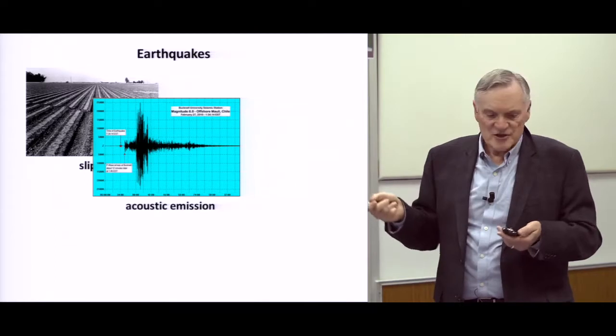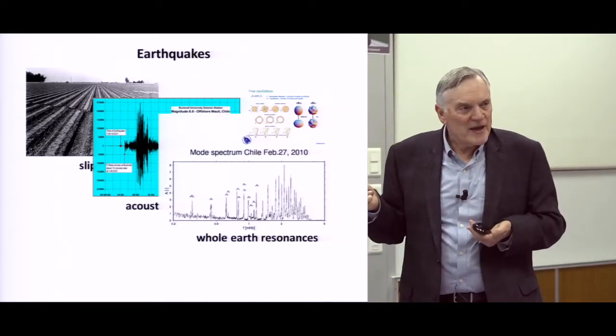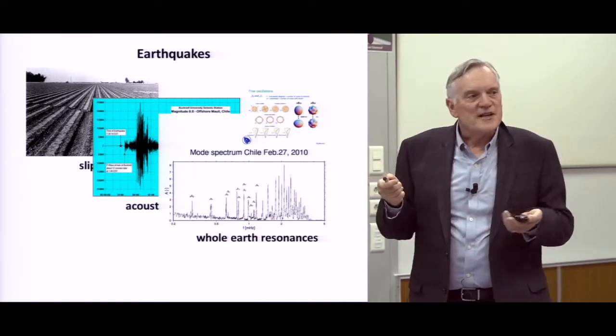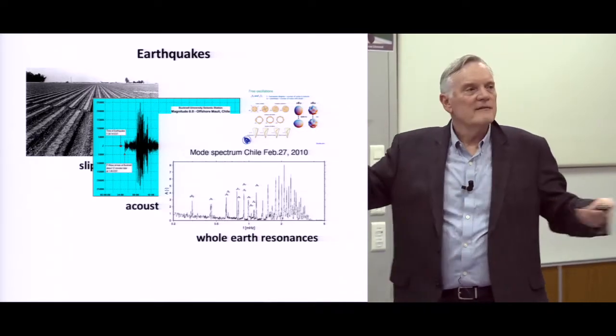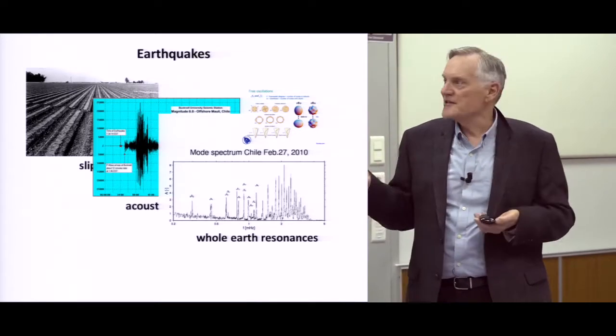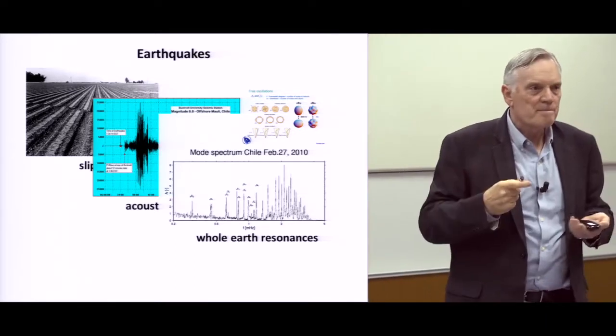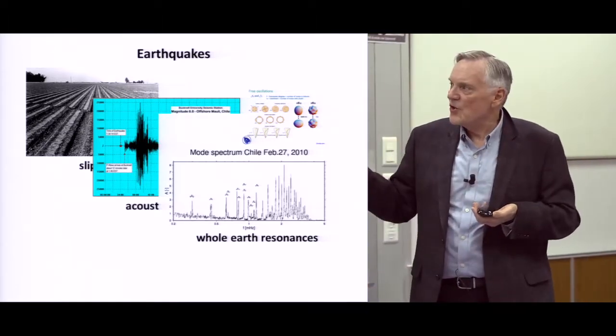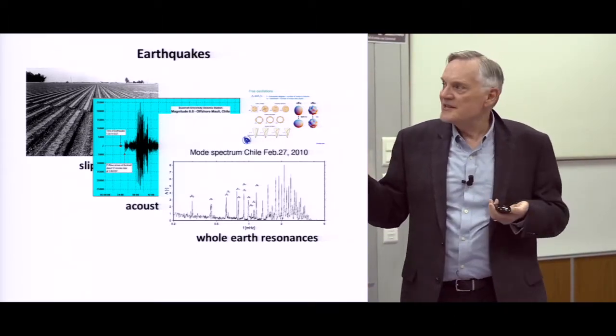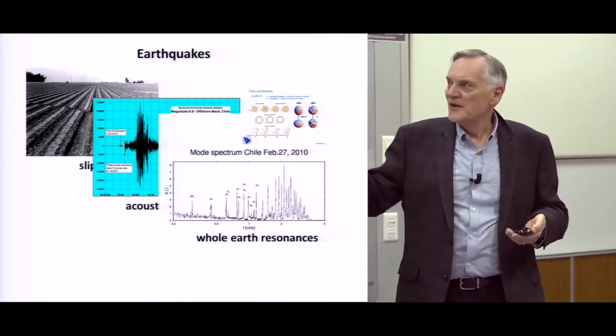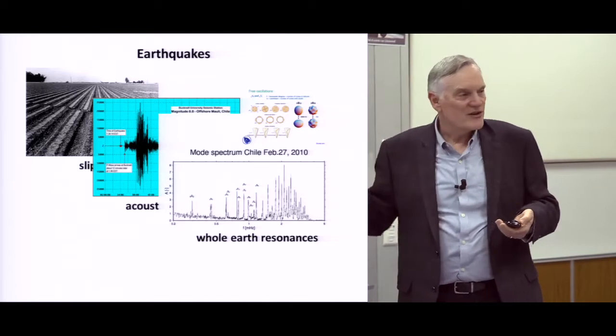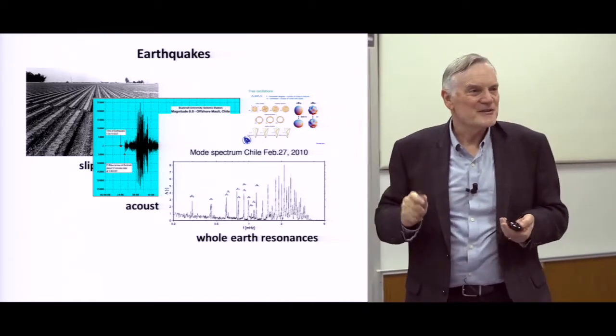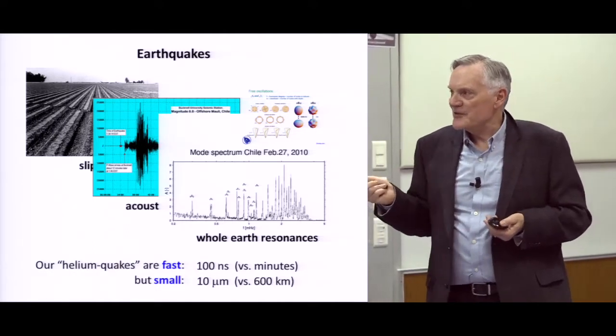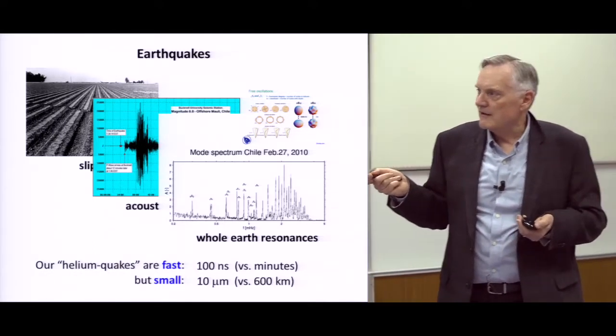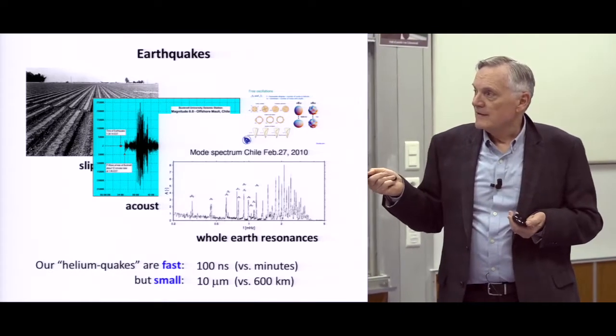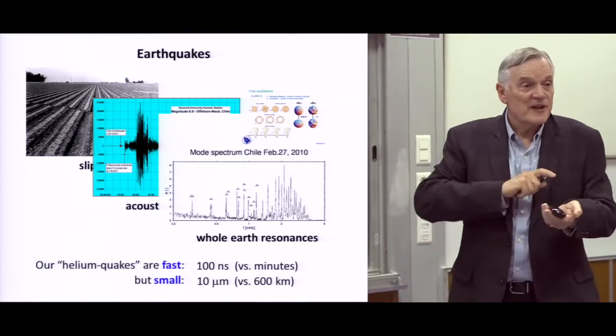So you have a slip event, acoustic emission, but then with a big earthquake, just like if we have a big slip, you can sit and wait and you find that the entire Earth goes into resonance. The lowest frequency resonance of the Earth takes about an hour, and there are higher frequency modes. They measure the whole spectrum of the Earth, and these are the acoustic resonances of the whole thing. So this is basically the path: the slip, the acoustic emission, and then the not so interesting resonance of the whole thing. The difference being that our little helium quakes are a lot faster, of order 100 nanoseconds, versus the minutes it took for that Chilean earthquake.